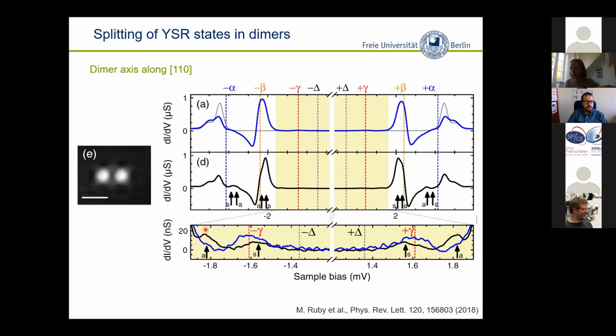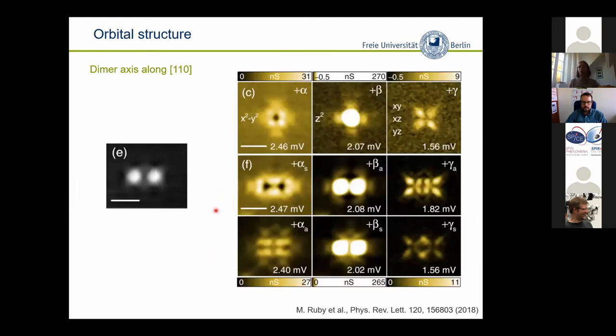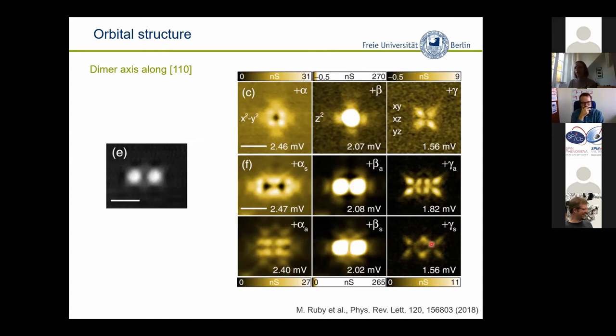Zooming into the low energy YSR states: the single atom shows only one peak, but for atoms placed in dimers you can make out two peaks. To confirm this, we again set the bias voltage at these particular energies and map out the differential conductance spatially. As a reminder, the upper panel shows the individual atom where we associated the shapes to particular d orbitals. In the lower panel, with two atoms close by, we again split the panel into very close energies — these correspond to the small splitting seen in the individual spectra. The shapes tell you the states derive from d(x²-y²), d(z²), and in-plane d(xz)/d(yz) orbitals.